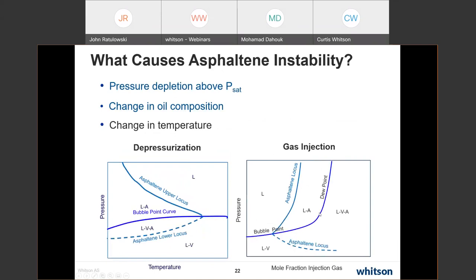Okay, what causes asphaltenes to come out of solution? There are really two main issues that we look at. Pressure depletion above PSAT, and I'll discuss that in the next slide. As I decrease pressure, I can come and hit this upper asphaltene locus, and I will continue to precipitate asphaltene until I hit the saturation curve. And after that, the actual solubility of the asphaltene in the liquid phase increases, so I redissolve it as I go down to lower pressures.